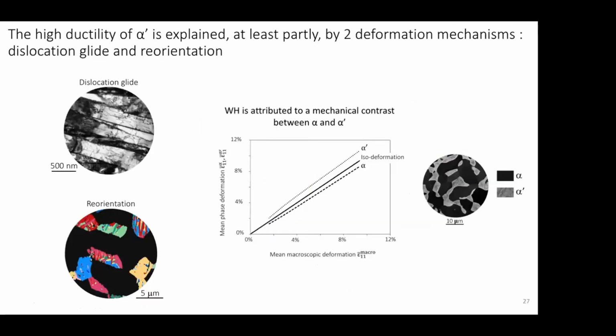So based on that, we think that reorientation can at least in part explain the ductility that we found in the martensite. To try to explain, we were at the scale of the martensite, but now we go back to the scale of alpha prime and alpha. The surprising observation was that we had a lot of ductility in the martensite, and we think that reorientation can at least partly explain why this martensite is ductile.